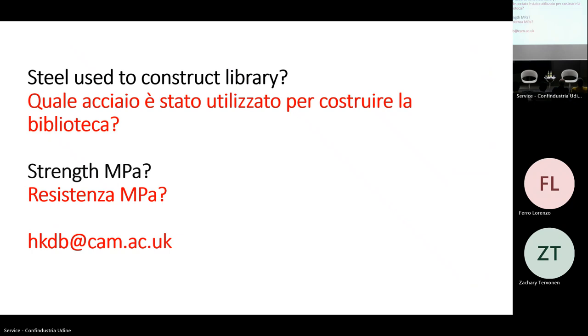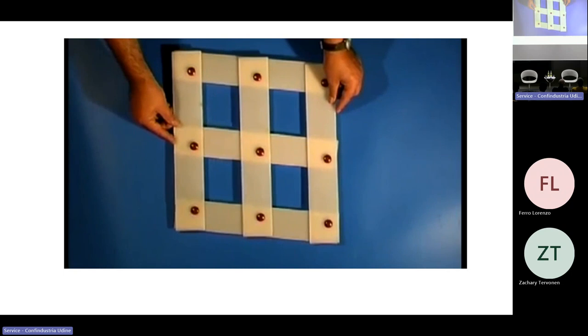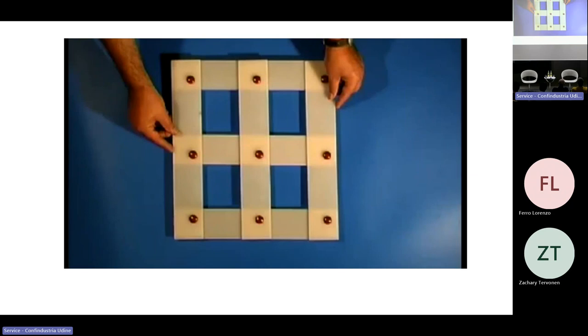So the way in which we can change the pattern in which the atoms are arranged, there are many different ways because, in order to control the structure, we alter the types of crystals there are in steels. And one way is to deform the pattern. In that method, you never actually break any bonds or change the sequence of atoms. Sometimes we call it martensite, martensitic transformation. But you notice that I can change the pattern and I can change it back, okay? So you can reverse that transformation without any change in the order of the atoms.